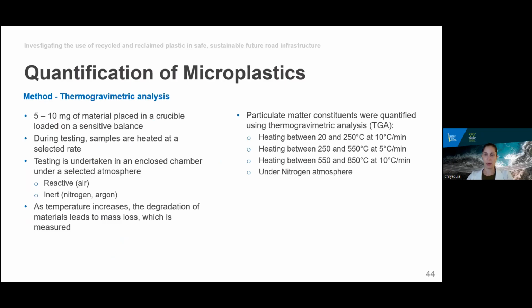To quantify the microplastics in the particulate matter, we used thermogravimetric analysis. This method analyzes between 5 to 10 milligrams of the sample of interest. The specimens are heated at the selected rate under an atmosphere of choice. Here we used a heating rate of 5 degrees Celsius per minute for high resolution measurements, and that was at the region of interest, which was between 250 and 550 degrees Celsius, and an inert atmosphere.